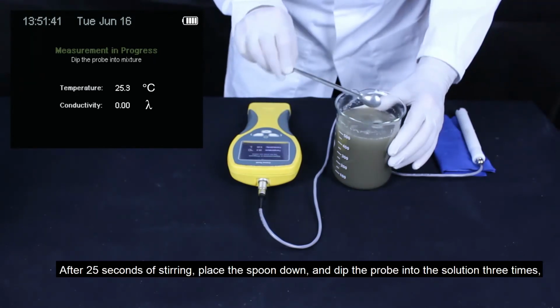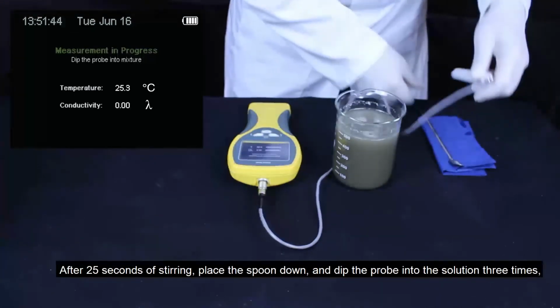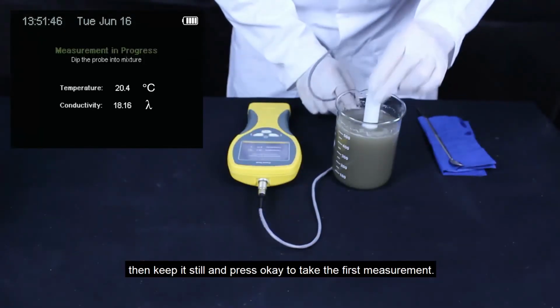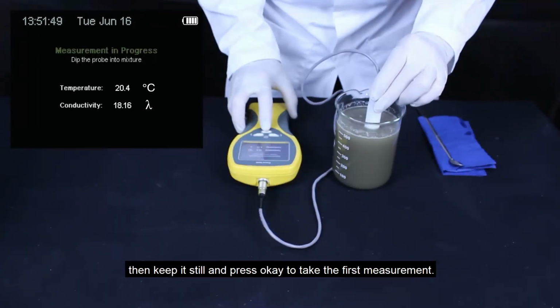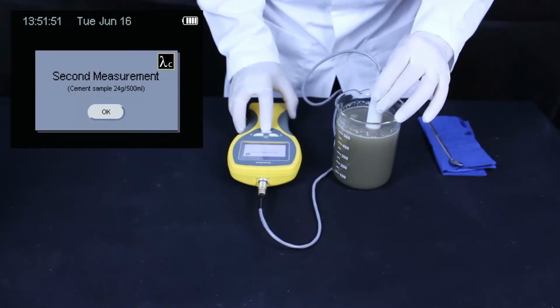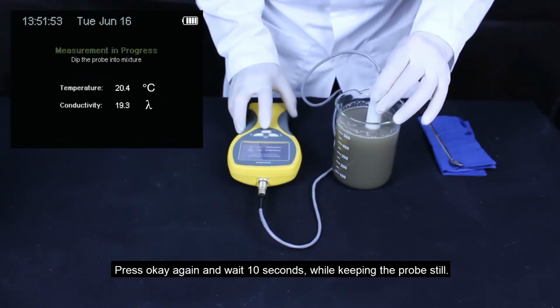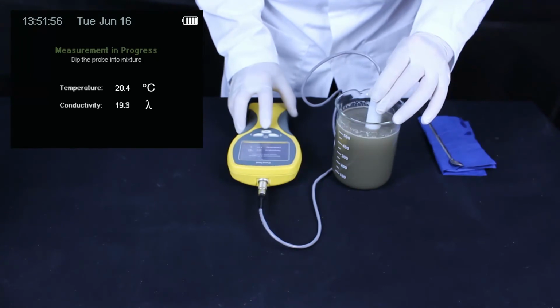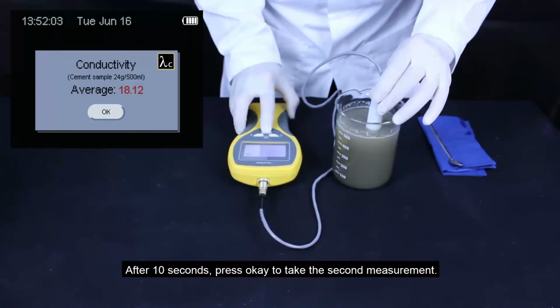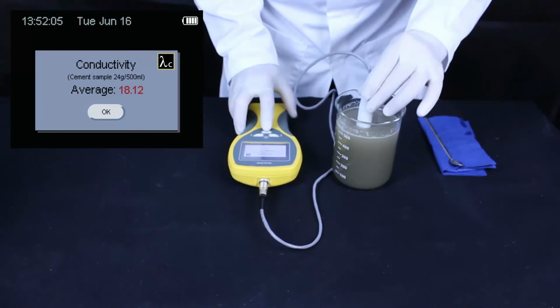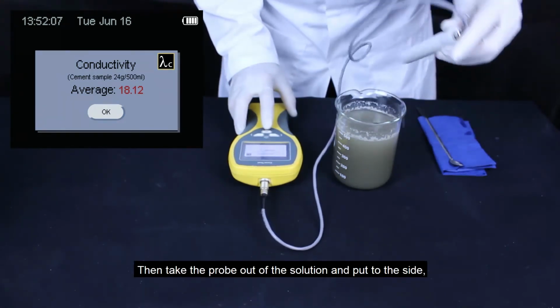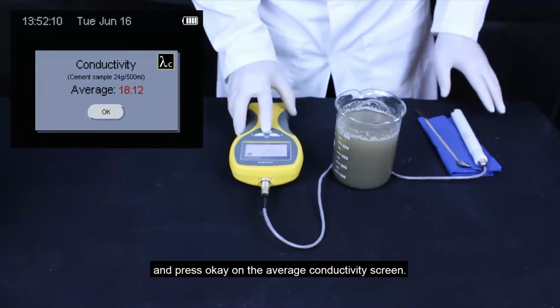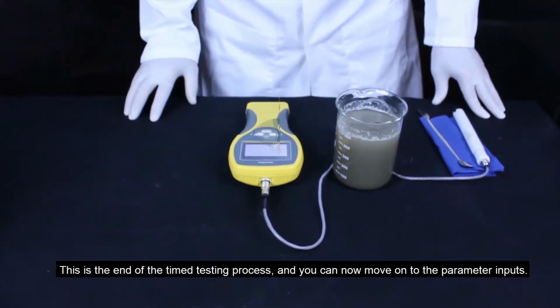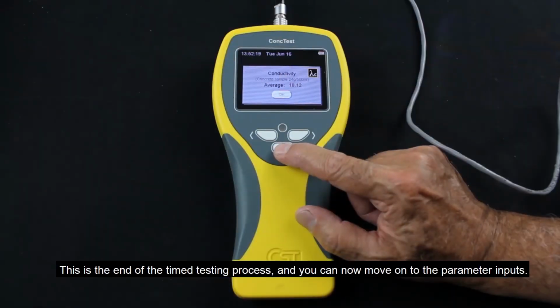After 25 seconds of stirring, place the spoon down and dip the probe into the solution 3 times. Then keep it still and press OK to take the first measurement. Press OK again and wait 10 seconds while keeping the probe still. After 10 seconds, press OK to take the second measurement. Then take the probe out of the solution and put to the side and press OK on the average conductivity screen. This is the end of the timed testing process, and you can now move on to the parameter inputs.